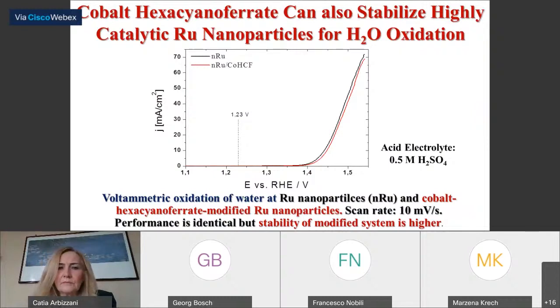This graph shows oxidation of water at ruthenium nanoparticles and cobalt hexacyanoferrate modified ruthenium nanoparticles. Performance of both systems is identical, but the stability of the modified one is much higher.